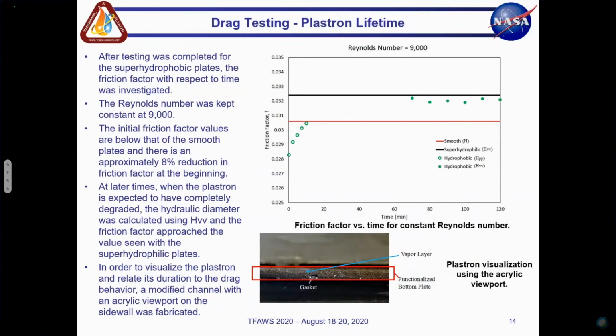Next, we go through drag testing for the plastron lifetime. So as I talked about, as we increase the flow rate or increase the time, you see this plastron or that air layer go away. So what we did was we kept this constant at a Reynolds number of 9,000, and we monitored the friction factor over time. So what we should see is the largest drag reduction at the start, and then over time, this friction factor decrease until you get almost to the superhydrophilic. As I talked about in the previous slide, the hydrophobic should fall slightly below the superhydrophilic because you still have the wettability effect despite both surfaces being fully wetted.